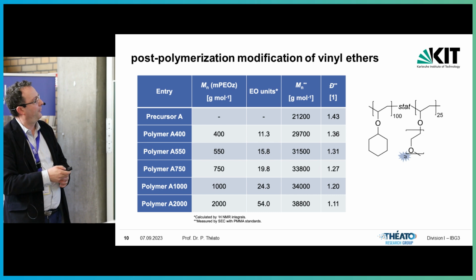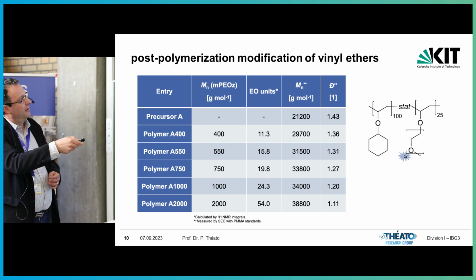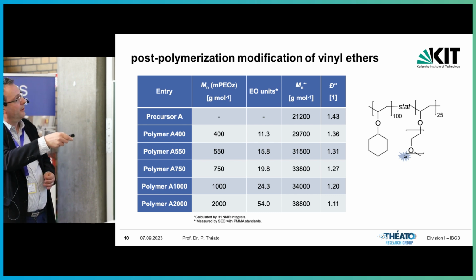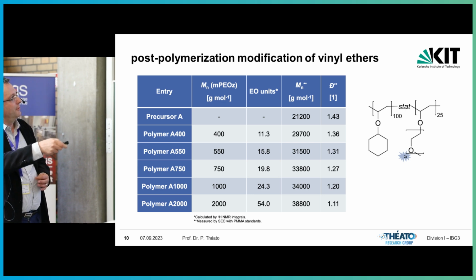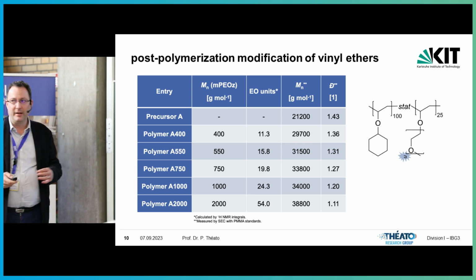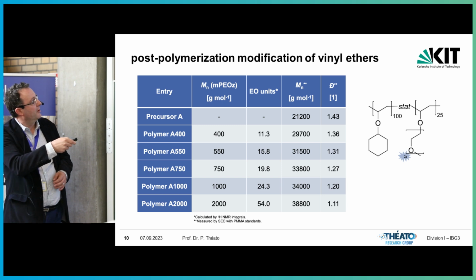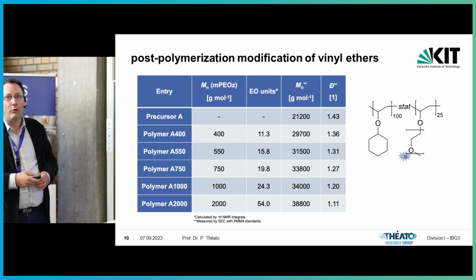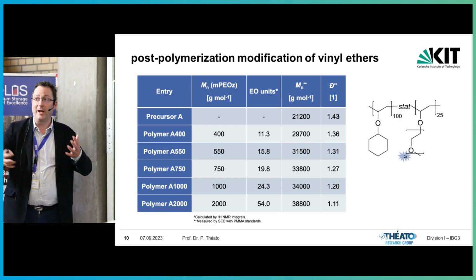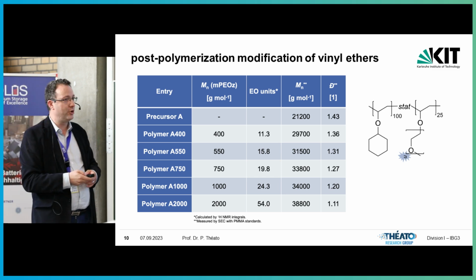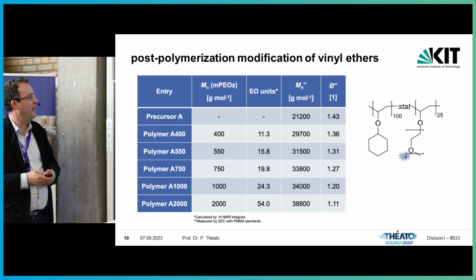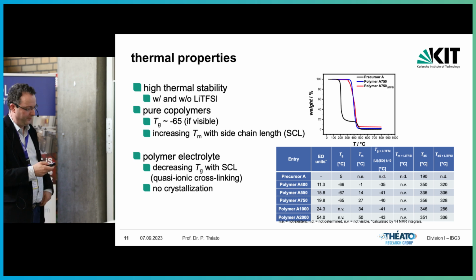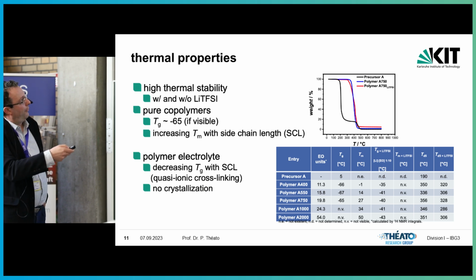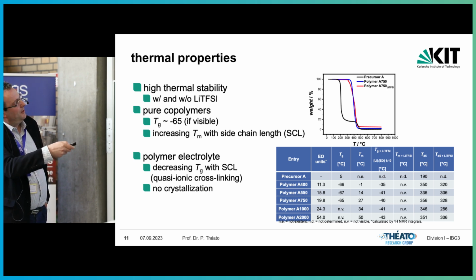So what we have now is a system where the backbone is identical, the ratio is identical, and we only vary the number of ethylene oxide units in the side chain. So if you calculate this in EO units, this is what you get, from 11 to about 54. And now you have something to play with relative to the lithium ion ratio and see how these systems behave in different parts. So thermal stability is pretty good.